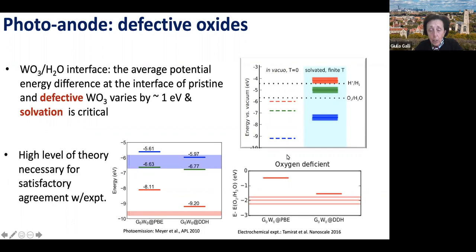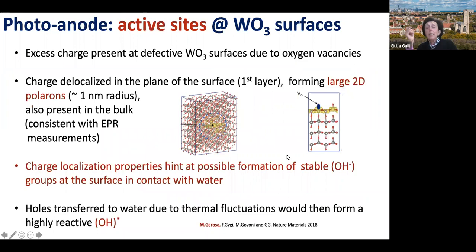So basically, after all the study, what we learned is the following. Because you have oxygen vacancy at the surface, you have excess charge. The excess charge at the defective surface forms a very large polaron, which in the case of tungsten oxide is a 2D polaron with about 1 nanometer radius.